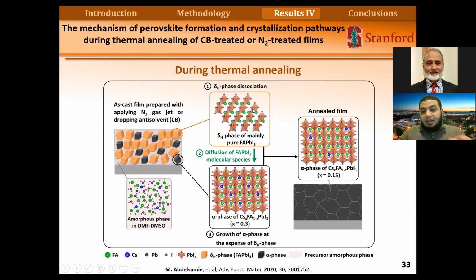And as we apply annealing, the annealing helps to dissociate the delta phase. And after dissociation, the molecules that are dissociated from the delta phase diffuse and contribute to the growth of the alpha phase. And with time, the FA dilutes the cesium, and we reach a uniform film with the final product. So we could reach this understanding by applying in situ characterization to understand the mechanism of formation.